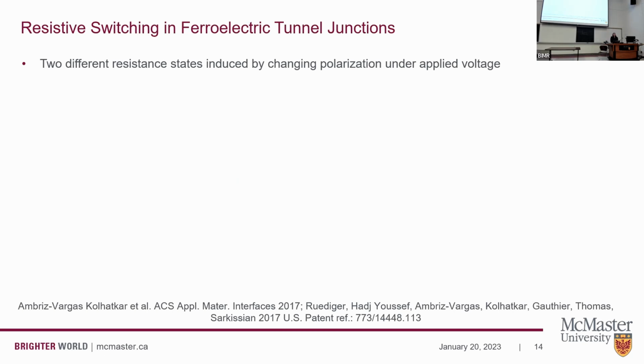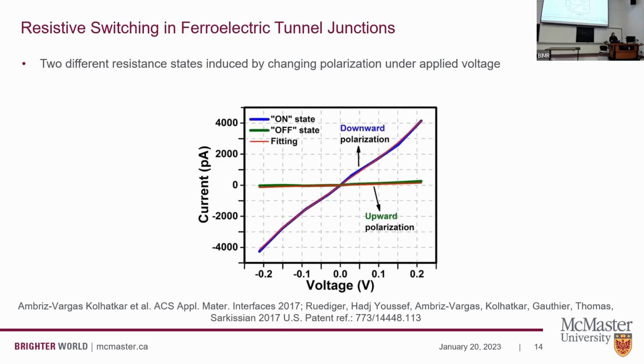Then the next step was to look at whether or not we could have some resistive switching in our devices. Just as a reminder, resistive switching means that we have two different resistance states, and we can go from one to the next by applying a voltage. This is a typical IV curve that we obtain on our ferroelectric tunnel junction. You can see that we have two different states here. The green curve corresponds to a state where a very, very low current can flow, and therefore indicates a high resistance state. This is polarization in our material pointing upwards.